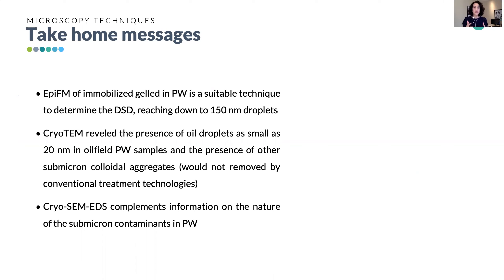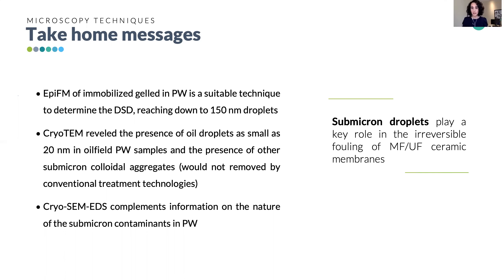These submicron contaminants would not be removed by conventional de-oiling technologies and might cause intrapore blocking in membrane filtration downstream. Cryo-SEM and EDS complemented information about the nature of the contaminants. Looking back at our initial hypothesis — that submicron oil droplets play a key role — after this research we might revise the statement to say we should focus on studying these colloidal aggregates instead, which could probably be another PhD.